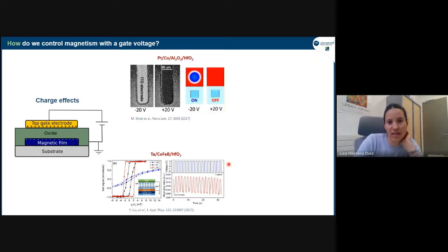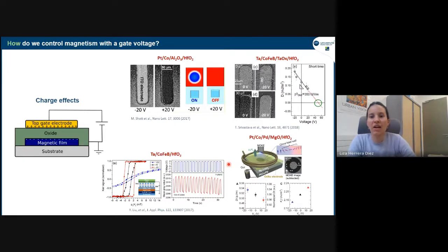And then other studies have shown, this is from collaborators at the Institut Néel in Grenoble, they could show that in platinum cobalt, they could actually write and erase skyrmions in the system just by the action of the electric field. And again, the group in Grenoble, but also all the groups in Japan, have shown that the DMI could also be affected by the electric field applied to the sample. So these are very nice perspectives, also from the side of the charge effects, even if these effects are volatile.